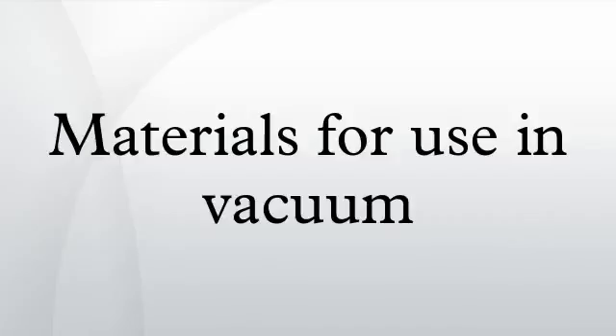Solders are sometimes unavoidable for soft soldered joints. Tin-lead solders can be conditionally used when the apparatus is not to be baked and operating temperatures aren't elevated. A better choice for vacuum systems is the tin-silver eutectic, Sn95Ag5. Its melting point of 230 degrees Celsius allows bakeout up to 200 degrees Celsius.